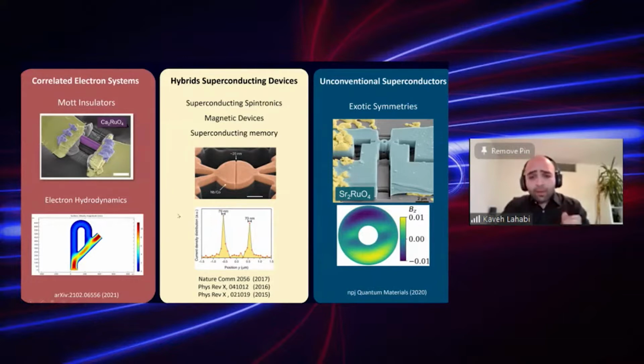But what I was missing was that in addition to my normal transport measurements, I needed a way to probe the local magnetic fields. So, for instance, here in this microstructured strontium ruthenate ring, theory tells me that because of the breaking of time reversal symmetry, my superconductor should have a local but finite field coming out of my superconducting ring.